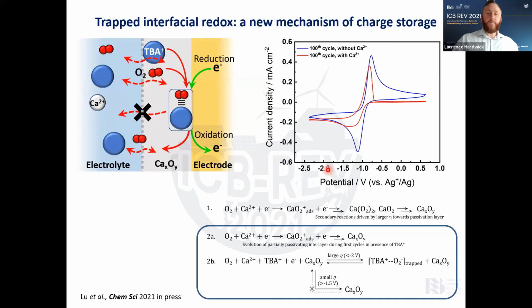So if we look at this phenomenon of trapped interfacial redox, what we found when we added calcium to our non-aqueous electrolyte was that it formed this calcium oxygen interlayer, and it provided an ability to trap tetrabutyl ammonium at the interface. This meant that it was much more readily available, as it's at the interface, as it's trapped, to be oxidized again. And so we observed this phenomenon.